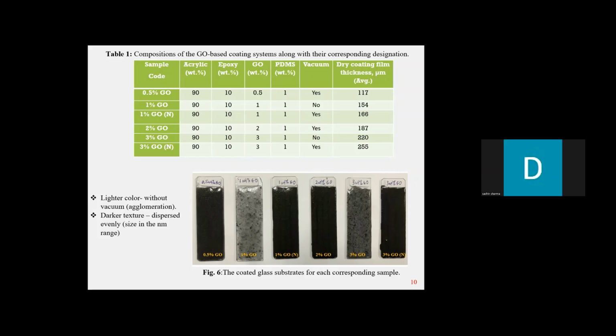I also added PDMS, which is polydimethylsiloxane. Why did I use 1 weight percentage as a consistent unit for all the samples? It is because polydimethylsiloxane enhances the surface wettability of the coating. Moreover, it has a Si-O-Si structure, and it will actually enhance the hydrophobicity of the coatings.